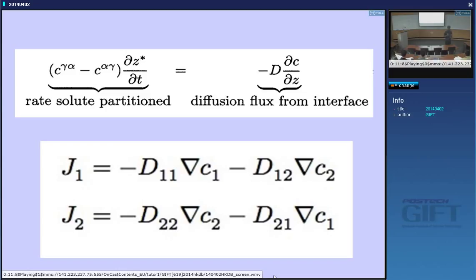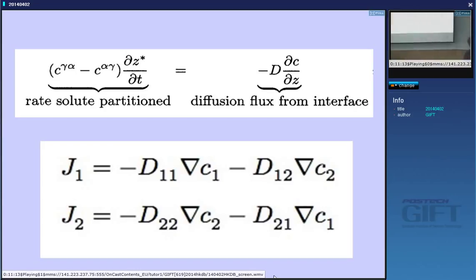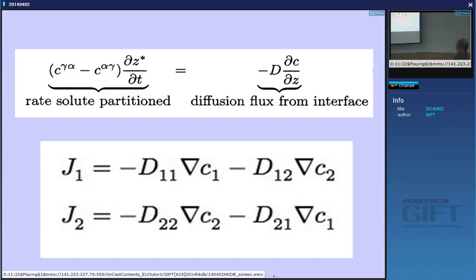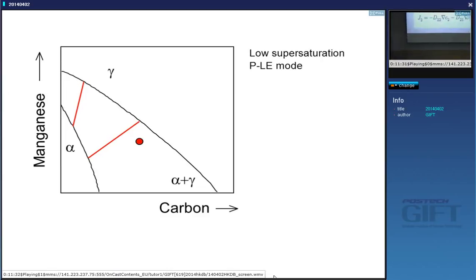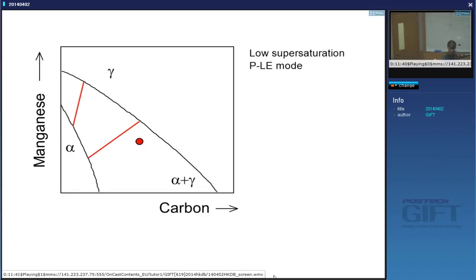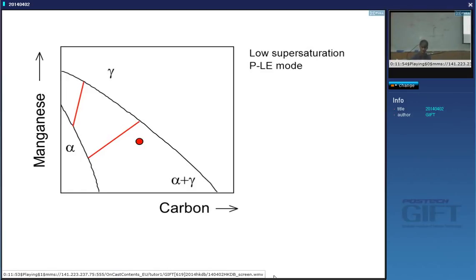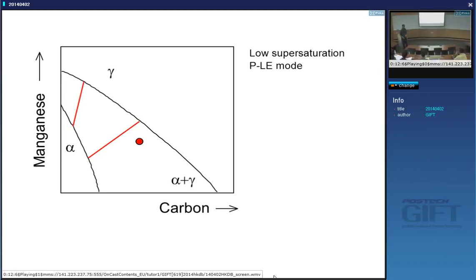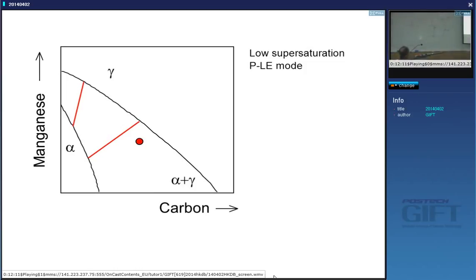These two cases are necessarily the two cases. One is where C-bar is close to the austenite equilibrium — that's low supersaturation. The other one is where C-bar is close to the ferrite equilibrium — that's high supersaturation. So I'm going to go through the two cases now. Imagine that we have an alloy of this composition in the ferrite plus austenite phase field. The tie lines are everywhere in that two-phase field, coming from thermodynamic measurements.